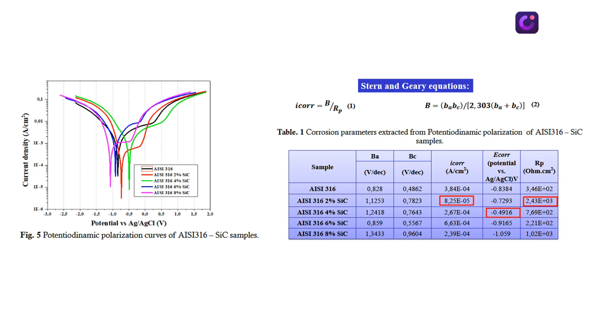As for the material with 6% reinforcement, it presents the highest corrosion current since there was a diffusion of chromium to the surface of the materials, as can be seen in the EDX mapping of the image, which increases the conductivity of this material and thus increases its electrochemical activity.